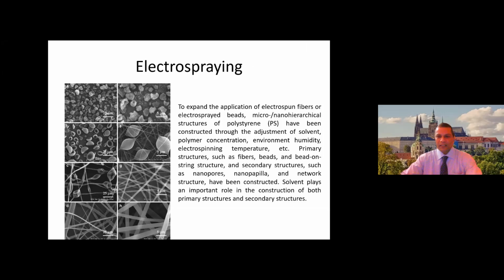Electrospraying is very similar to electrospinning, but it doesn't form fibers. It only forms a porous, more of a nanoporous membrane by deposition of these droplets. How is it possible? If we reduce the concentration of the solution and thus don't allow the solution to be converted into some tubular fiber-like structure, but just split it into very fine droplets which are deposited onto a substrate, and these droplets create a membrane which has the same level of porosity and features like the nanofibrous material, and it is easier to form, and they have the same level of filtration efficiency and permeability as nanofibrous membrane, and easy to form. That is why in many cases it is better to adopt electrospraying rather than electrospinning.